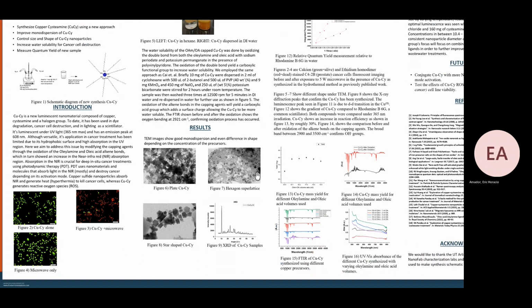However, our results give us highly monodispersed nanoparticles, as seen with these TEM images. In Figure 7, we have an average size of 20 nanometers in diameter, and depending on the precursor concentration, you can control the dispersion of the nanoparticle. So for really high concentrations, you can produce very highly monodispersed nanoparticles, as seen in Figure 7, or if you have very low concentration of copper and cystamine precursors, you will get larger nanoparticles.